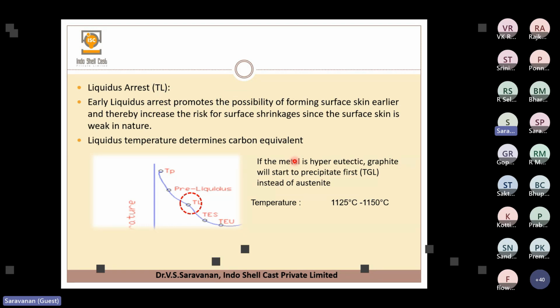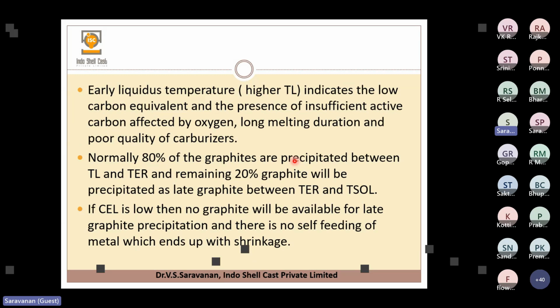This liquidus temperature is actually derived from the carbon equivalent. In the software they have a lot of formulas, based on the temperature and the carbon at that particular time, and they create these arrest points from that. From an arrest point we can also calculate the carbon equivalent, vice versa. This will form between 1125 and 1150. An early liquidus temperature indicates low carbon equivalent and insufficient active carbon, because at that time the first austenite started growing.